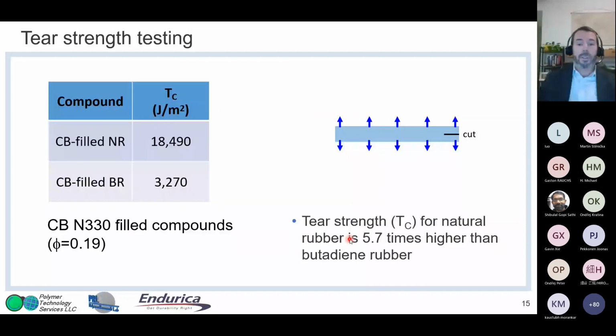And if you use that geometry for the same 2 materials I showed you earlier for fatigue crack growth, what you can see is, and maybe this is not surprising, that the tear strength of carbon black filled natural rubber is over 5 times the value for butadiene rubber. I think this is well understood.